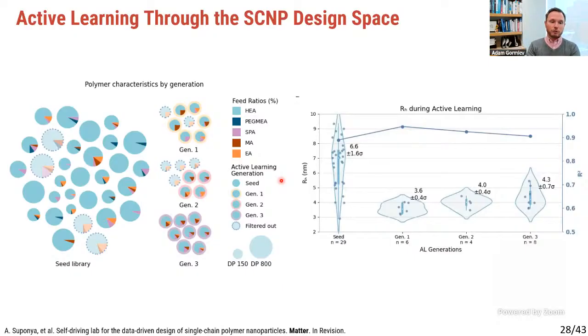We've done this now several times. This is just the most recent one. This ran over last Labor Day weekend all by itself, ran the whole weekend by itself. And basically what we saw, really interestingly, is that it pretty much learned the structure function landscape very quickly. We didn't see that all the time. Most of our other campaigns did worse. This one did it very, very fast. In fact, it learned very quickly after the first generation, and then it actually started to get worse as time went on, which is really fascinating.